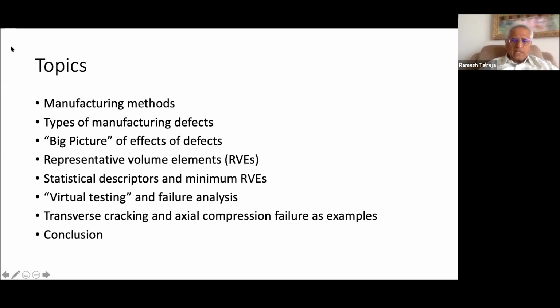But for failure analysis, one has to do a different type of RVE. And in doing so, one has to make use of certain statistical descriptors that are properly suited to account for the manufacturing induced defects. Then the next step is to conduct so-called virtual testing on the computer. Having RVE is like having a specimen that you go in a laboratory and do testing on, but this particular RVE is the virtual specimen on which you do testing. And at the same time, with computational mechanics, you do failure analysis.